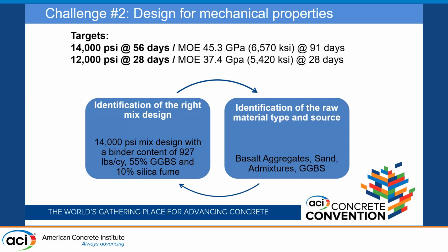Okay, concrete compressive strengths. Again, all tested with 6x12 cylinders on site. 14,000 PSI was the requirement at 56 days. And the modulus of elasticity was 45.3 GPa or 6,570 KSI at 91 days. The design that was used achieved an average of 14,500 PSI at 91 days and a modulus of elasticity of 47.9 GPa or 6,945 KSI. So just pushing over the requirements.